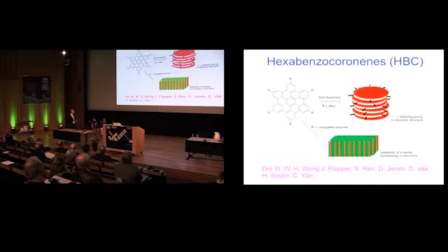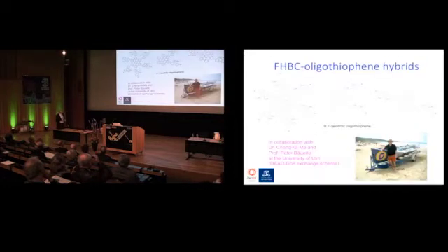And we have used molecules, I'm not going to talk about them, called hexabenzocoronenes as the donor material because they stack. And actually, Professor Aida was the person who demonstrated how beautifully these molecules can stack. So the better the stacking, the better the order, and the better the charge extraction is. So you need a supramolecular ordered material to get the charge out, and the fullerene also has to order itself. And our collaborator in Ulm is Peter Bäuerle, and he has helped us decorate these hexabenzocoronenes with light harvesting branches, like the dendrimers that were spoken about by Professor Aida.